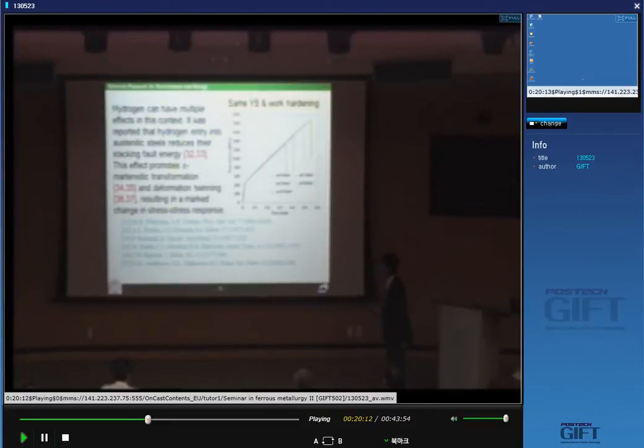This reduction in stacking fault energy promotes epsilon-martensitic transformation and deformation twinning, which results in a marked change in the stress-strain response.